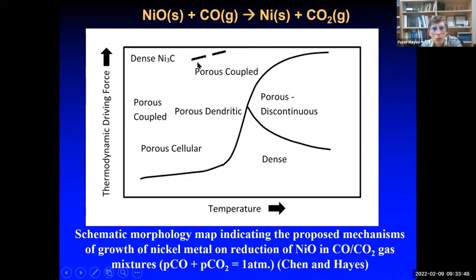So at that critical range here, we can get porous nickel forming at low temperature. And that forms various structures from what looks like a coupled structure to a cellular structure to a dendritic structure. At high temperature, we have porous discontinuous pattern, which is the formation of a dense layer and then the bursting of that layer. And all the way across the temperature range at low thermodynamic driving force, we get the formation of dense nickel layer.